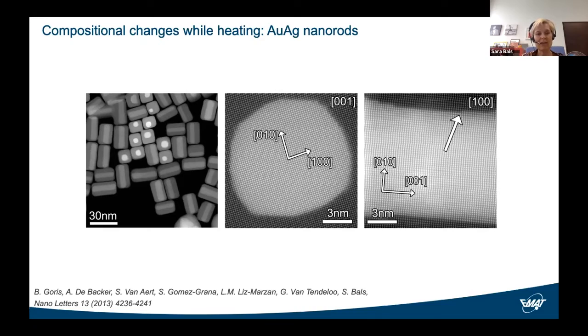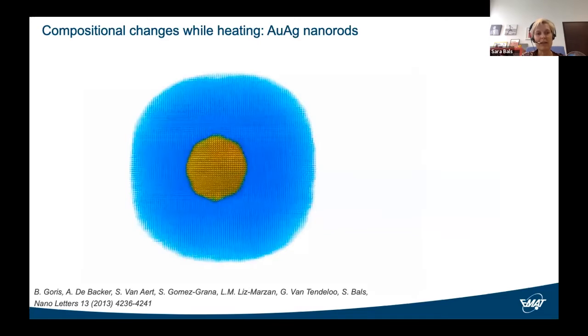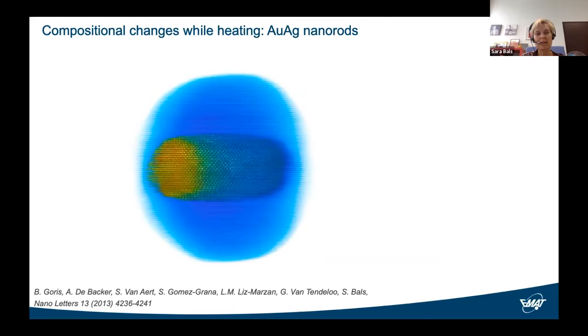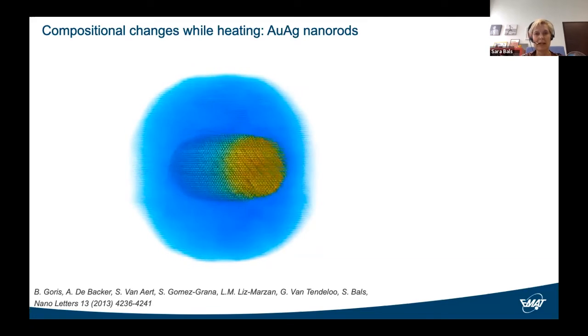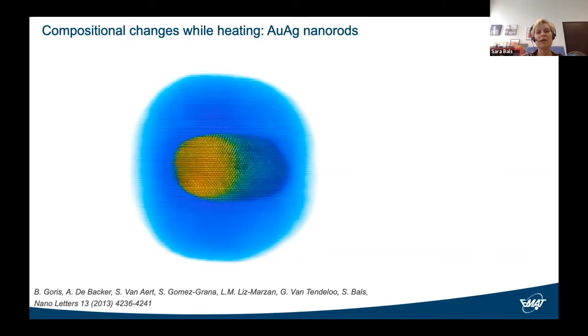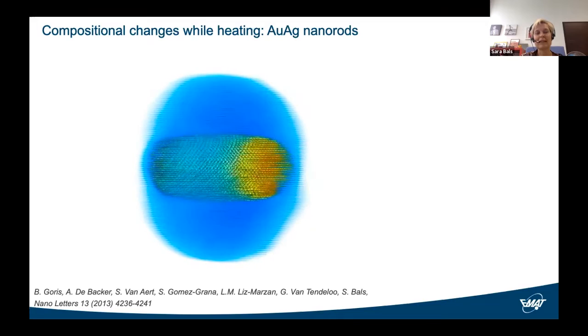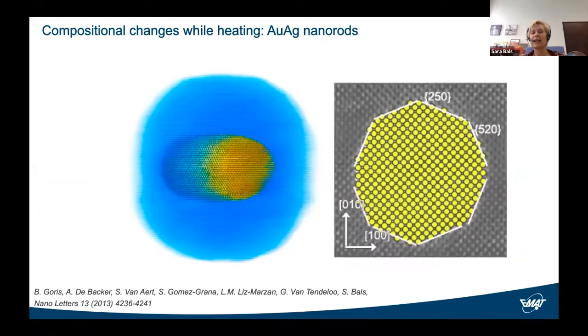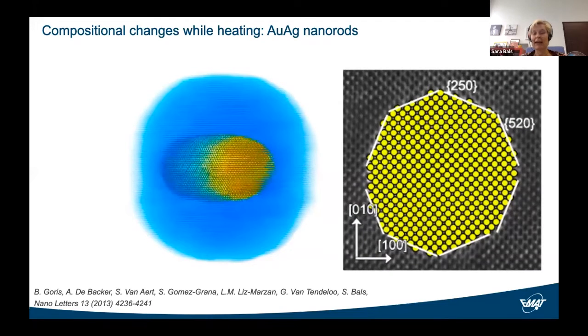And this is a relatively old study where we investigated the atomic structure. You can see that again, we are able to reproduce the lattice of the gold and the lattice of the silver. And we also investigated the interface between the core and the shell in more detail by analyzing the intensities, and we could determine the type of crystallographic facets at the interface between core and shell.